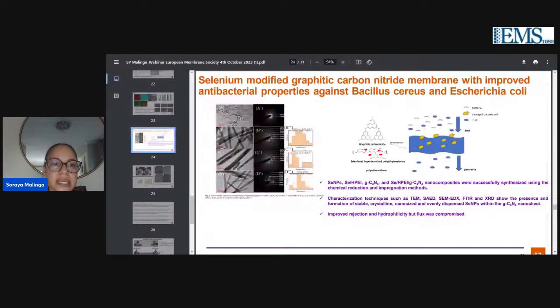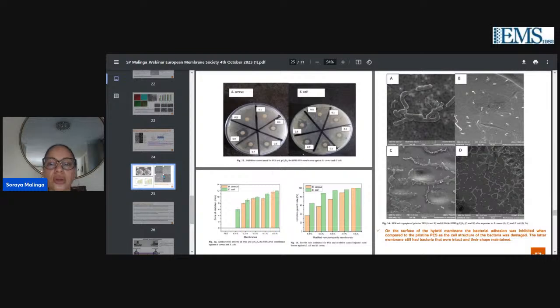Recent work, we have also used selenium, this time prepared in graphitic carbon nitride. We used phase inversion. What we got with our particles, these were not spheres but rods. We then exposed these as well to microbiology analysis where we did inhibition. So we would cut the membrane, put it on an agar plate that has the targeted bacteria. Then we measure the zones of inhibition. We could find that as we increase the concentration, the zone of inhibition became much bigger, which showed a positive